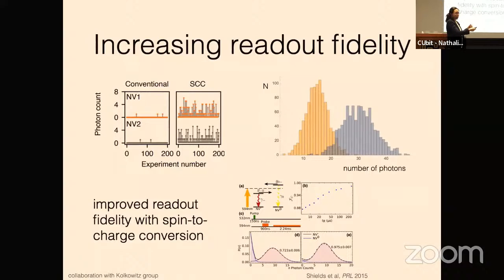So you can sort of map spin ms equals 0 to one charge state and ms equals plus/minus 1 to a different charge state. And the reason you would want to do that is it's actually very easy to read out the charge state because these things fluoresce in totally different bands. So all you have to do is sit there and count photons in the right band. And it turns out that you can get much, much higher fidelity measurements.